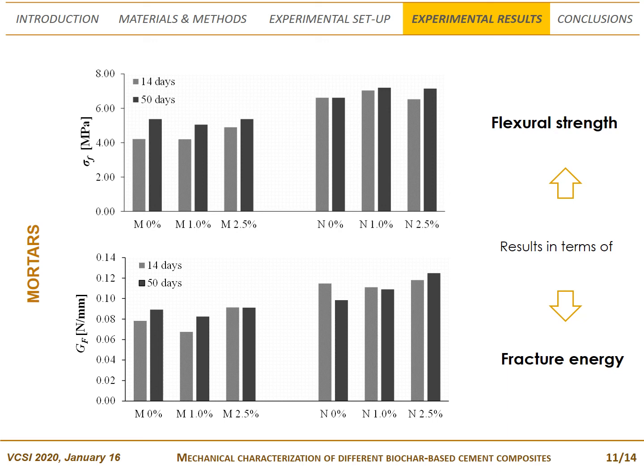This could be explained by considering that the value of fracture energy of the control batch at 14 days presents a high scatter, resulting in a mean value at 14 days quite greater than the corresponding one at 50 days.